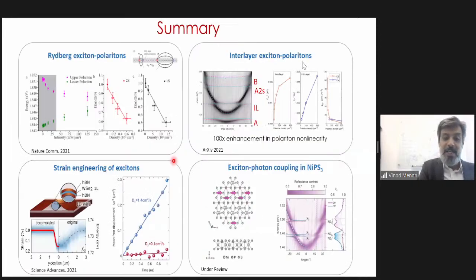So I think with that, I want to conclude and leave some time for questions by pointing out that strong light-matter coupling and the formation of these quasi-particles called polaritons is a nice platform to study nonlinear optics in the weak pump limit. We showed the use of Rydberg polaritons, the interlayer polaritons in these 2D materials, and also this idea of strain, and then more recently this idea of using correlated materials in cavities and being able to either probe them or affect their overall electronic response.